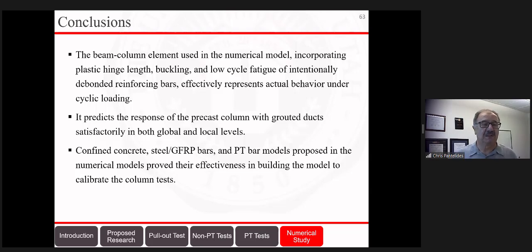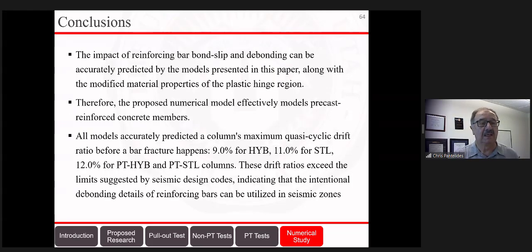So the beam column element that was used in the numerical model with the plastic hinge, the buckling, and the low cycle fatigue effectively represents the actual behavior. And it predicts the response of the precast columns with grouted ducts, both at the global and local levels. And the confined concrete for steel, GFRP bars and PT bars models, all of this prove their effectiveness in building the models. And the bond slip was modeled, debonding was modeled, and we think that it's effective in doing this. The hybrid was within very good agreement, predicted bar fracture 9%, the steel 11%, and the post-tensioning at 12%, which is pretty much what happened in our experiments.